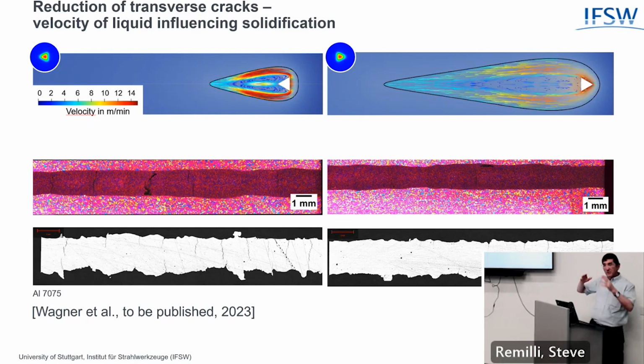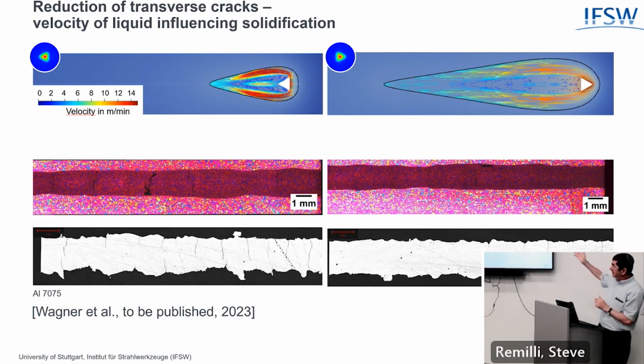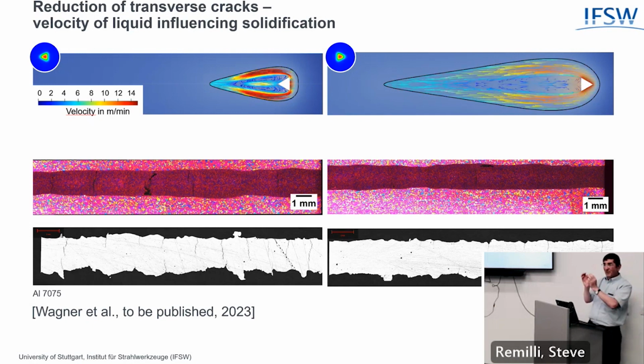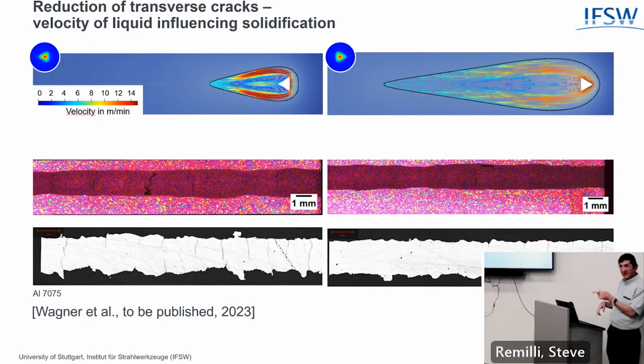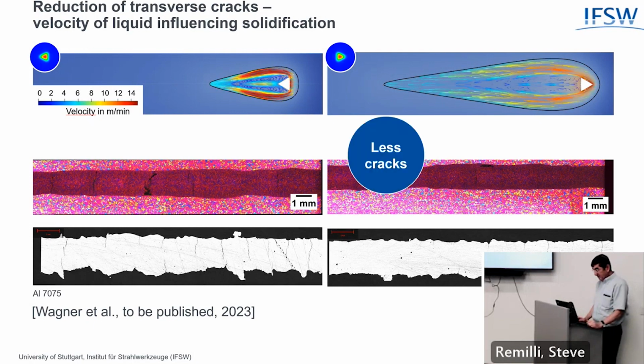The reason it happens, by the way, is because when you have the currents, you create a pressure gradient inside the melt pool, and the pressure gradients control the motion of the molten material between the grains as they resolidify. Because in the resolidification, you have grains that resolidify, and if there's voids between them, you get cracks over there. But creating these pressure gradients inside the melt pool during the resolidification makes sure that these cracks don't happen. There's a talk, I have a link at the end to the talk of the head of the IFSW. It's fascinating, you should listen to it. It's just incredible science, how they developed this.